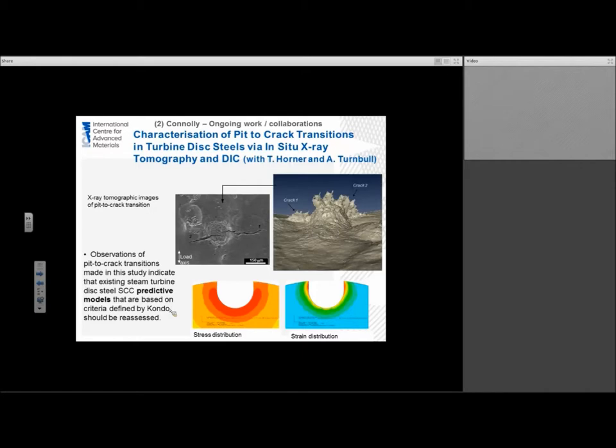We also took a look at doing some finite element modeling on the stress states and the strain states of these types of pit morphologies. We see that we get actually the highest stress, of course, at the bottom of the pit, but the highest strain levels are at the mouth of the pit. In this system, at least, the initiation of cracking or the transition between pitting and cracking has occurred at the highest strain location, not the highest stress location. From this work, any observations of pit-to-crack transitions that use predictive models based on the criteria defined by Kondo had to be reassessed because Kondo's model always says that you will get crack initiation at the highest stress state.